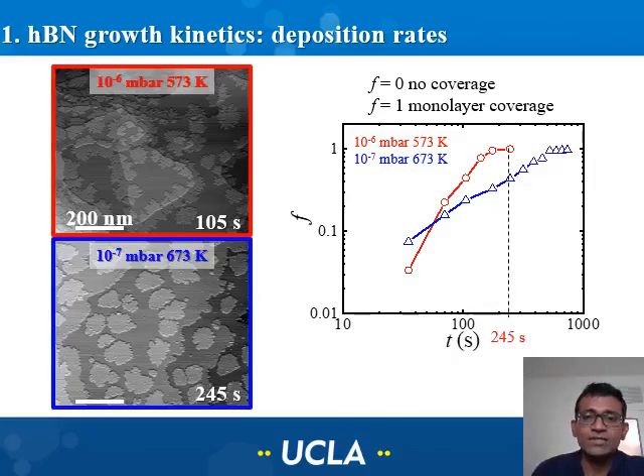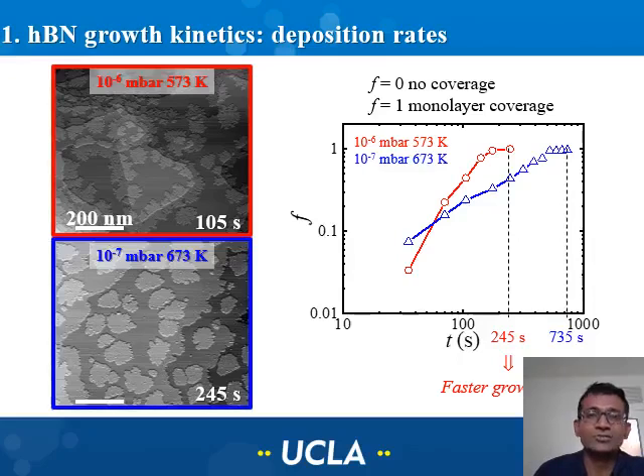And what you notice is that at high pressures and lower temperatures, a complete monolayer coverage is obtained within 245 seconds of deposition, whereas at lower pressure and higher temperature, it takes approximately threefold higher time, meaning that at the higher pressure and lower temperature, the deposition occurs at a faster rate.